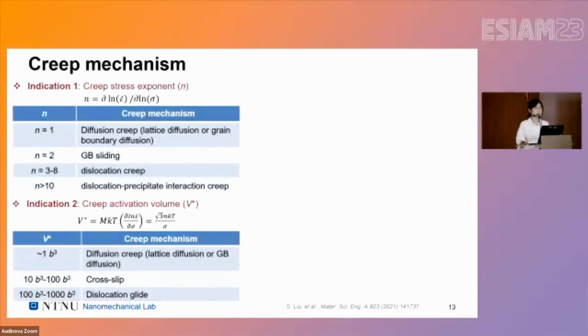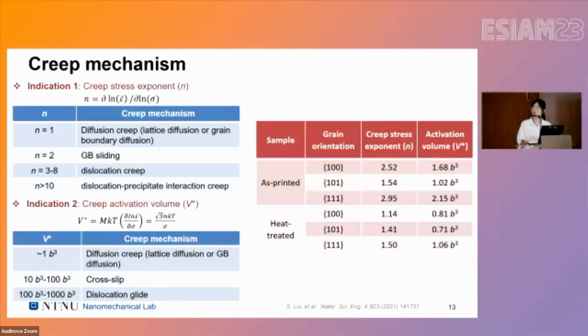If we would like to further understand the creep behaviors and estimate the creep mechanism, there are two indicators. The first one is the creep stress exponent, and the second one is the creep activation volume, because creep is a thermally activated behavior. As you can see in these two tables, different values indicate different creep mechanisms. Then we summarize the results of these two indicators in different grain orientations and samples, and we found that lattice diffusion is the dominant mechanism in these two samples.